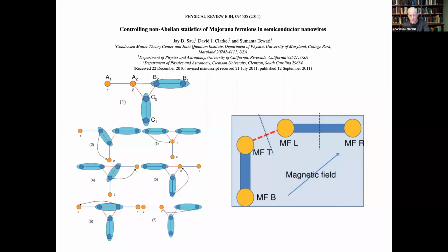It's about the exchange interaction with this field. Now, you say, exchange interaction, I thought this was an insulator. Indeed it is. It's the exchange interaction just from the scattering of the Cooper pairs off of the surface of the ferromagnetic insulator that is enough to rotate them in spin space. The long theory about this, I won't spend a lot of time talking about.